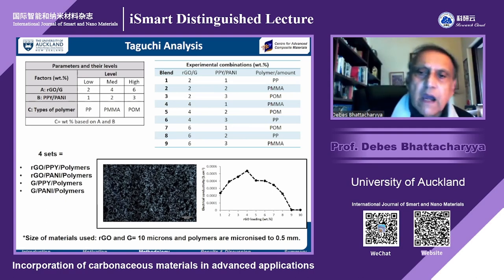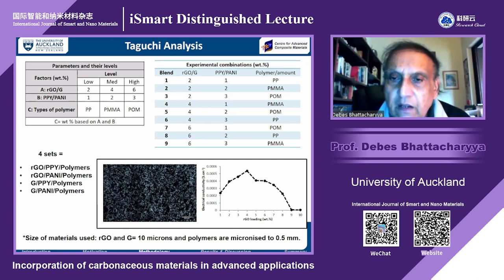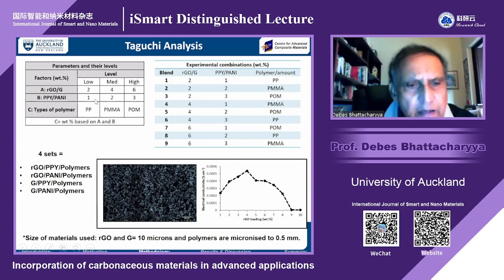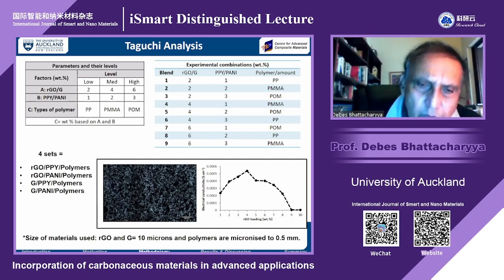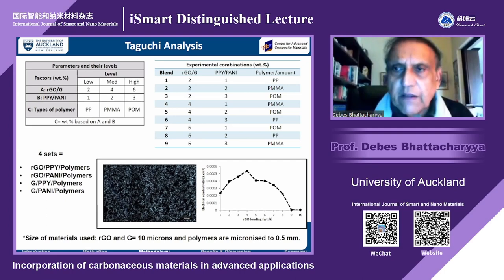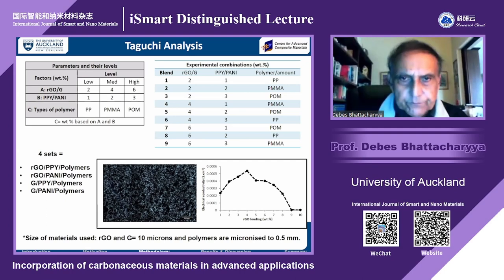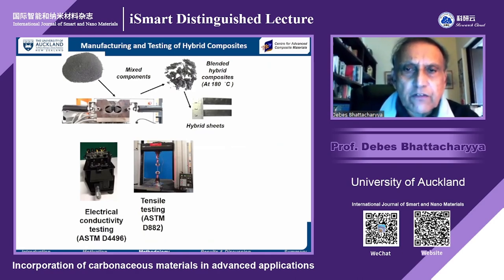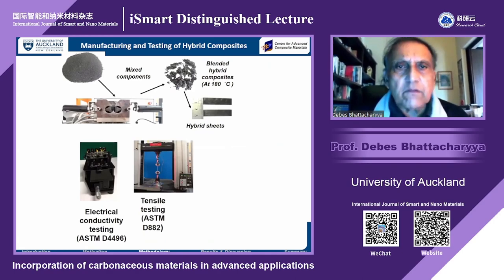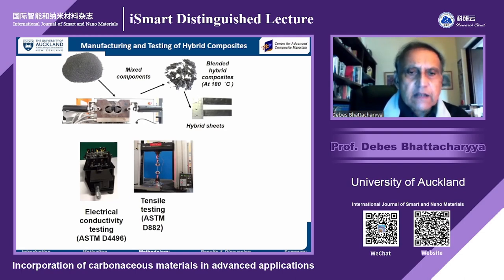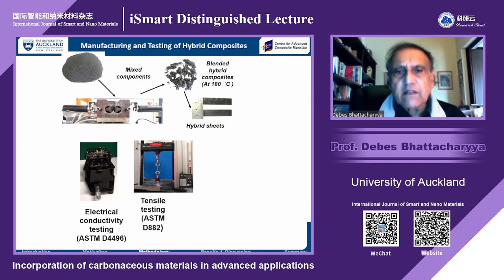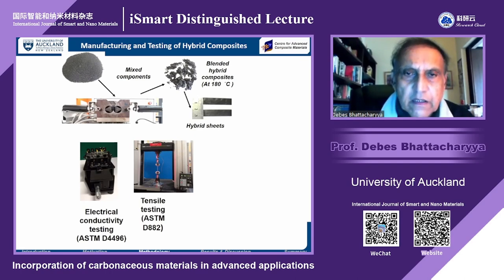And by varying RGO loading, we thought electrical conductivity reaches a maximum and then comes down. This was very early work, so we did not simply depend on that. I'll show you, we modified the experimentation technique, we modified the results, we modified various things. And the quick manufacturing process was a twin screw extruder, mixing the compounds, hybridization, then electrical conductivity was tested and tensile testing was done in an Instron machine.